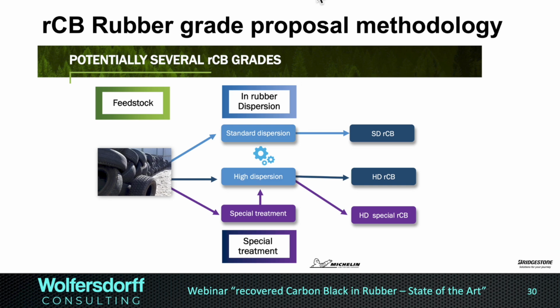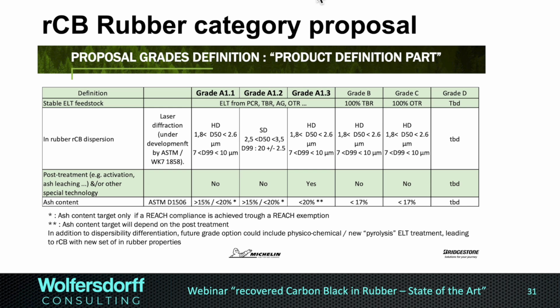Because I talked with one of those two tire makers about activated recovered carbon black, they like the idea of a special treatment and the combination of a highly dispersible recovered carbon black and activation to make it a little bit more reinforcing in rubber. And we got this kind of great proposal where you can note that the stable ELT feedstock is one of the discriminators. So the grades A1.1, A1.2, A1.3 are all from a set mix of PCR, so car, TBR, truck, ag, agricultural, and OTR, off the road, so, for example, mining tires. But the mixture has to be consistent. And the grade B could be 100% truck, and the grade C could be 100% OTR. And that was just to give an idea about the feedstock governing the recovered carbon black product.